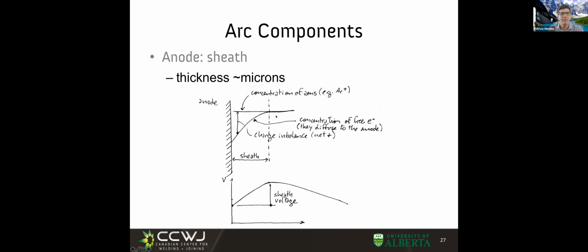So what do we have? We have a boundary layer, much like the same as we have discussed in the heat transfer class. And in this boundary layer, we have a temperature gradient for the ions. The ions have a temperature gradient, and the non-ionized atoms. They are slow, they have a temperature gradient. But the electrons, they keep moving, they kind of overshoot this cooling of the ions. And then we have a difference in temperature. We have the ions that are colder and the electrons are hotter. And then very near the anode, the anode absorbs all the electrons that are nearby. So here we start to have a depletion of electrons, right? And in this depletion of electrons, we have a charge imbalance.